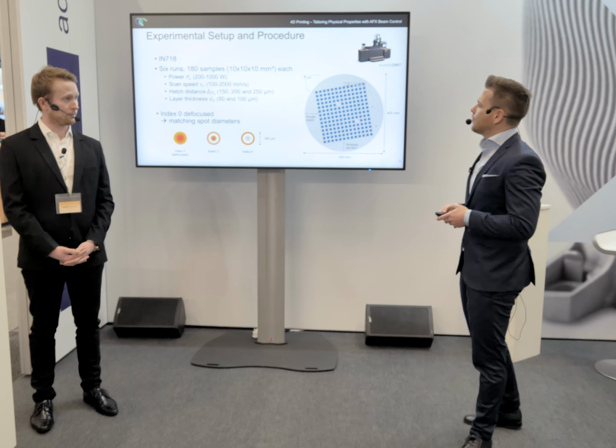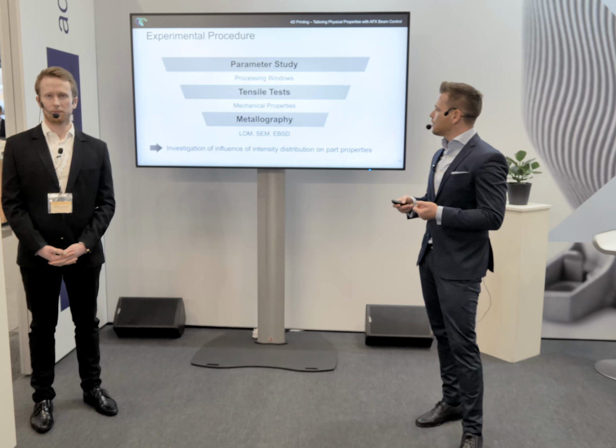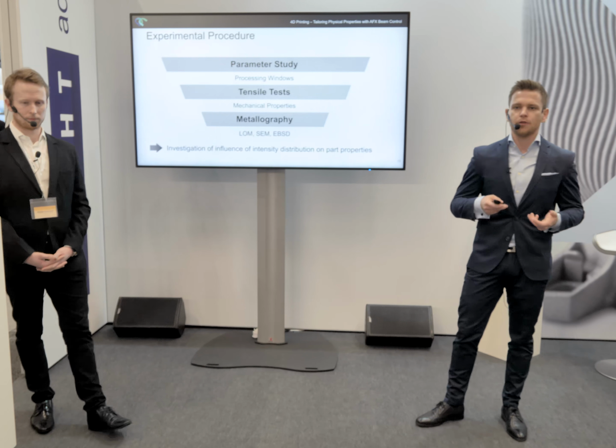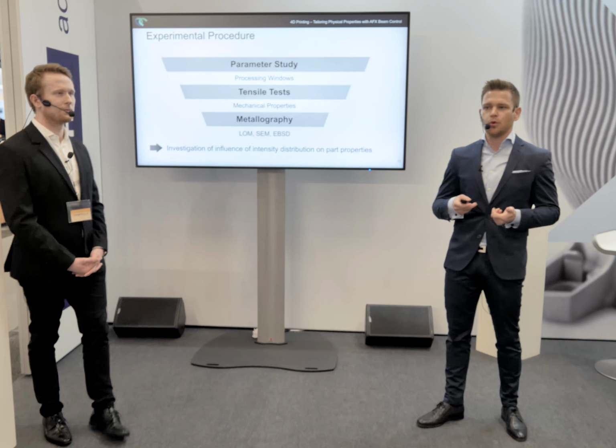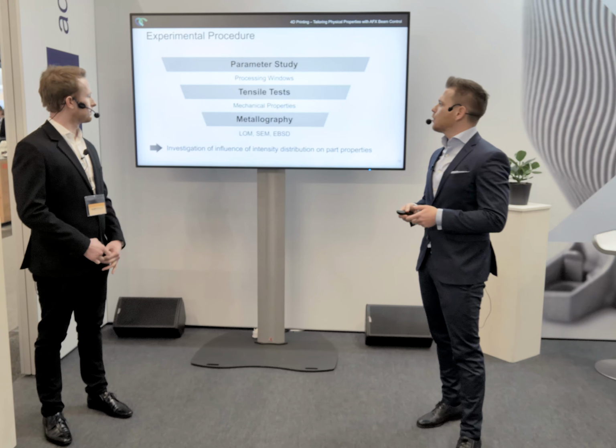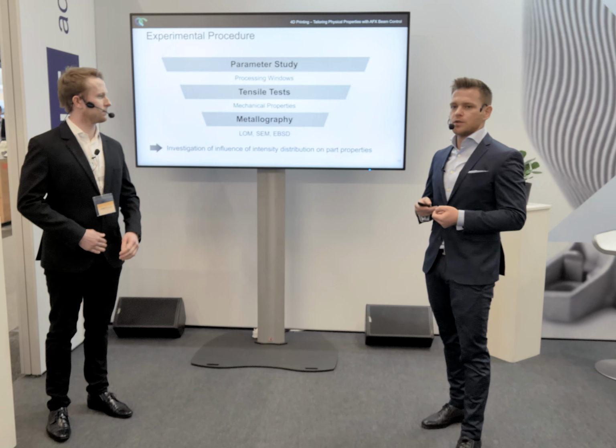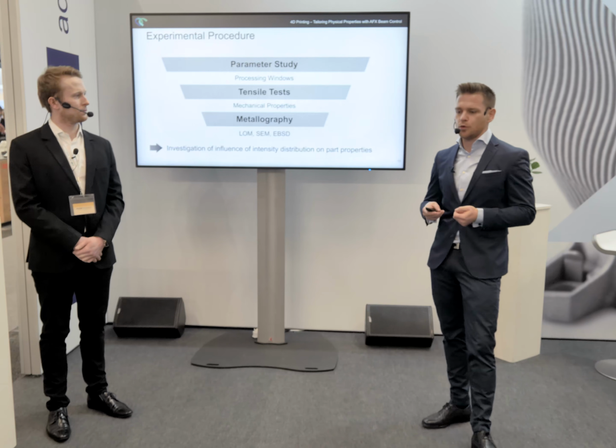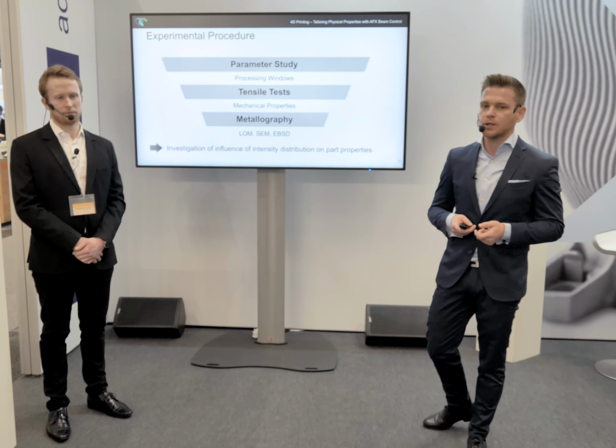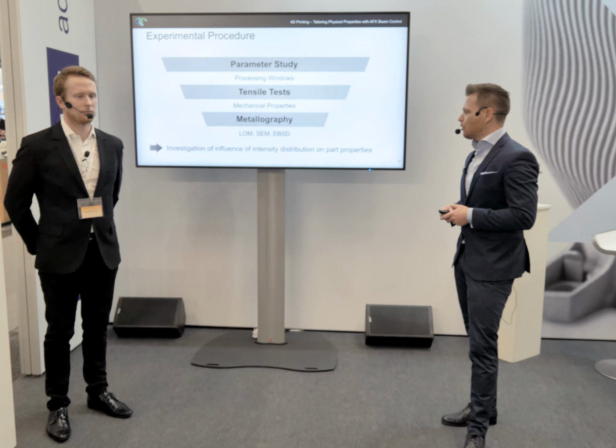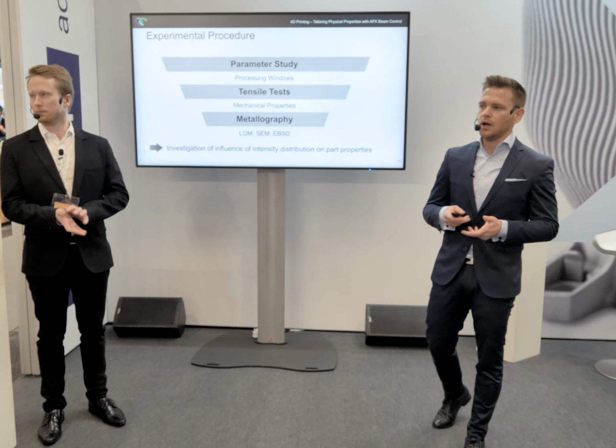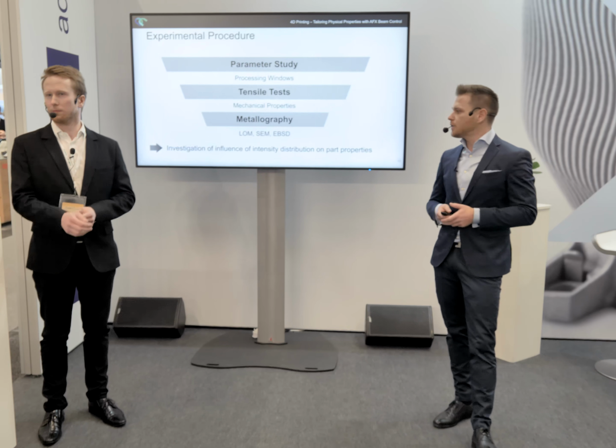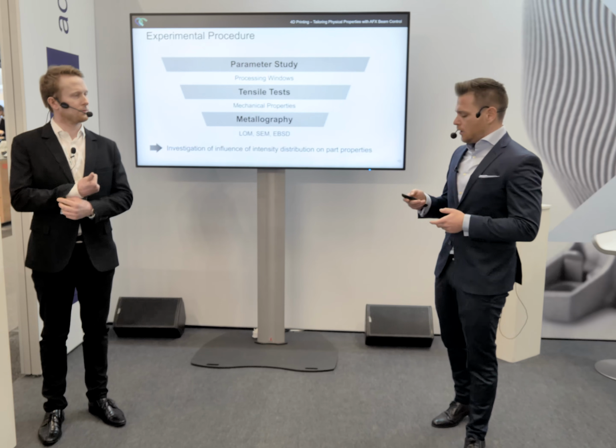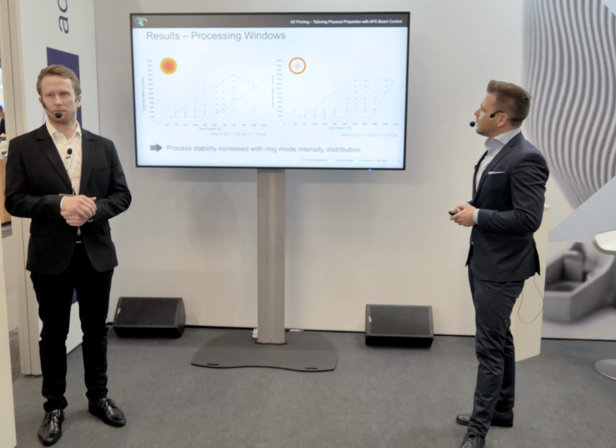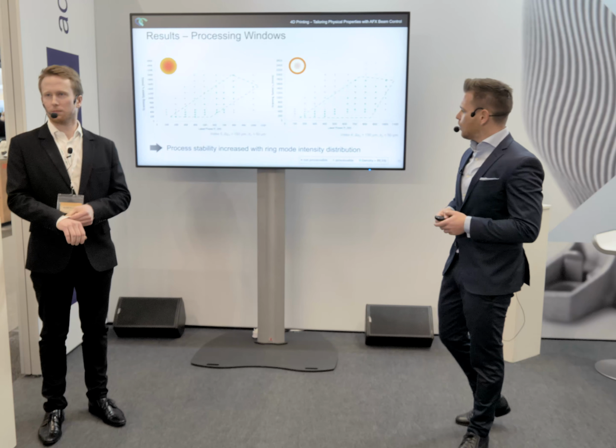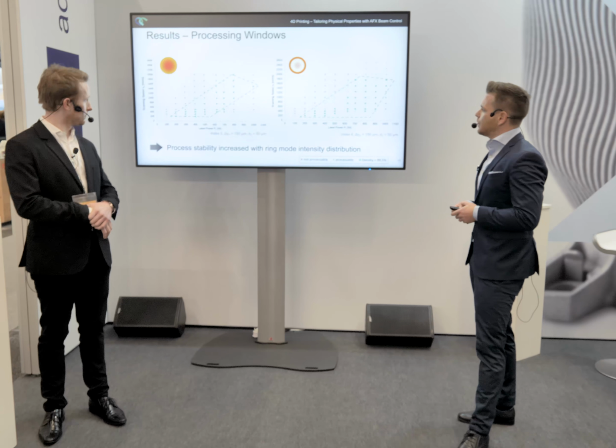And out of this, we generated processing windows just to get a first impression of the productivity and processability. These were the base grounds for the decision to select further parameters to produce and test tensile specimens, as well as the metallographic analysis via LOM, SEM, EBSD, and EDX. Coming up to the results, here we see the processing windows for index 0 and index 6.